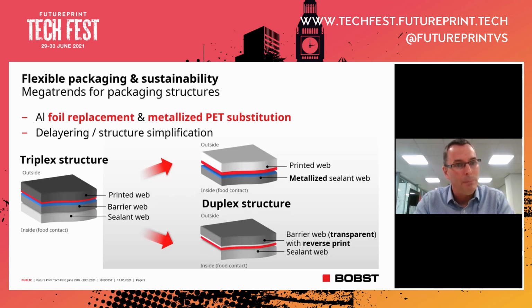For the lower example on the lower right-hand side of the slide, here we're considering a transparent barrier using aluminium oxide or silicon oxide within the structure. And because the AlOx or the SiOx layer is transparent, we have the option of integrating the transparent barrier layer onto the printed web, where we would then, on top of the AlOx or the SiOx, reverse print onto that barrier web, therefore combining the print and the barrier functionality on the single web.